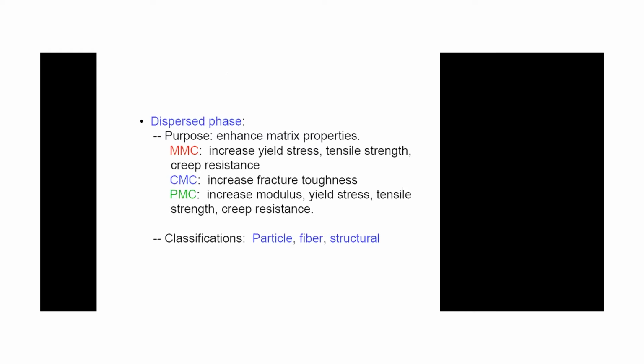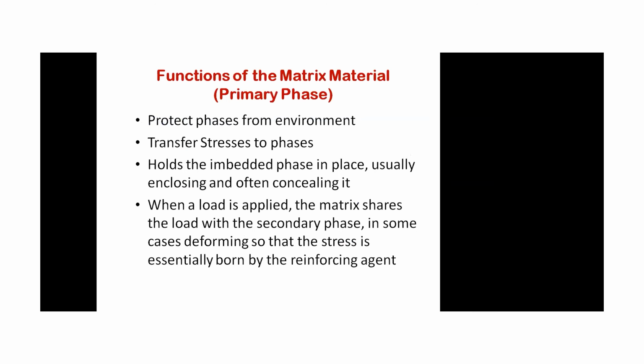So the purpose is different. For MMC, we are adding ceramic to increase the yield strength and creep resistance. In ceramic matrix composite, because ceramic has a lower toughness, we are adding metal or other things to increase the fracture toughness so that cracks won't propagate. In polymer matrix composite, we are adding metal or ceramic in order to increase the modulus, creep resistance, and yield strength. And we can add any kind of reinforcement in terms of particle, fiber, or structure.